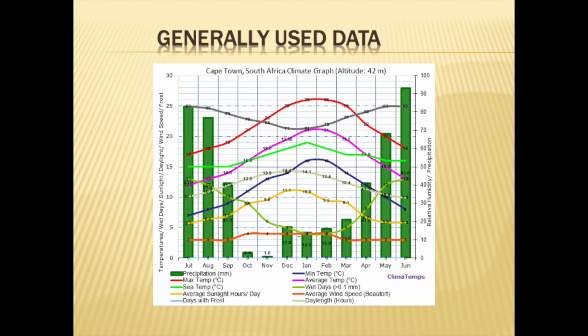But I would just now caution people in terms of when you use the standards, going back to try and find the reference. So I've put together a few slides, and if we can just have a look at those, it will define some of the dramas that we can have if we don't look a little more carefully at what is around the area where we will be specifying a corrosion protection system. ISO 9223 classifies the environment by looking at the four metals, but in addition to that, it has things like time of wetness, which to some extent depends on humidity, temperature, rainfall, and what else have you. Now, this is a map of data that you can get down in Cape Town.